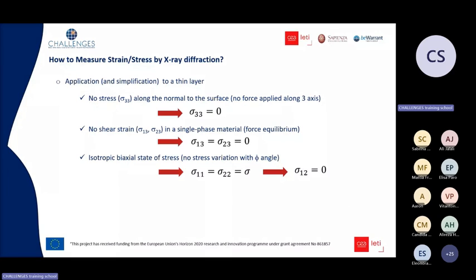And if we look now at the previous relationship between strain and the different components of strain or stress, it can reduce to this simple equation where the strain along the psi direction is given. The strain varies linearly with the sine square psi value and the stress applied on the material. So here the S2 and S1 are what we call the X-ray elastic constants. I will come back on that later.